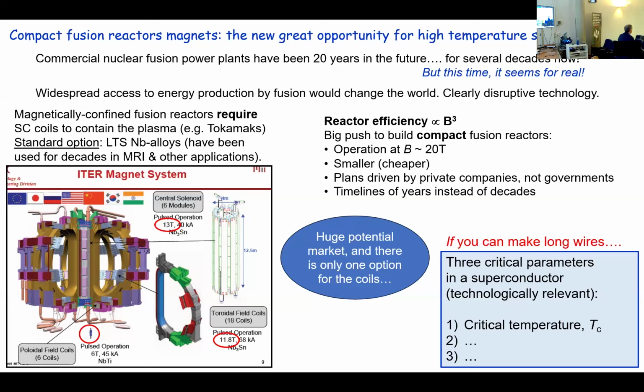Thanks for the talk. Have you checked if there's any difference between the critical current during irradiation and afterwards? Oh, I never did that in the old times. We didn't care. We wanted to see how Jc went up. But there is a huge interest in that. I'm working now with the MIT people, in collaboration with a student called Alexis de Vitre, who has done lots of those things. They irradiate at cryogenic temperatures with protons and see the evolution, and then without removing the sample, they irradiate at 20 Kelvin, anneal to 40 Kelvin and back, and measure up to 60 Kelvin. And then above 100 Kelvin or so, I don't want to say wrong things, but at some point below room temperature, they start to see annealing effects.